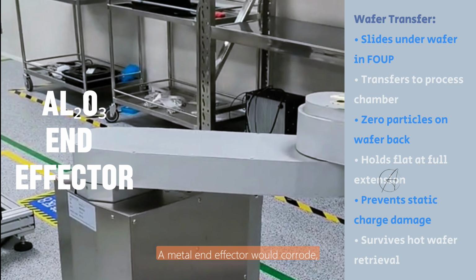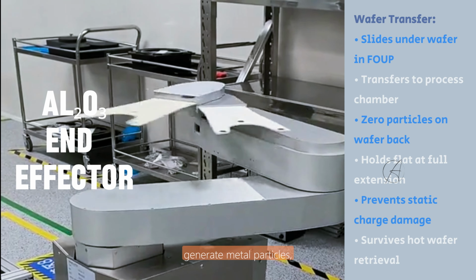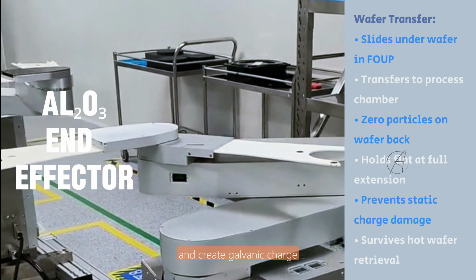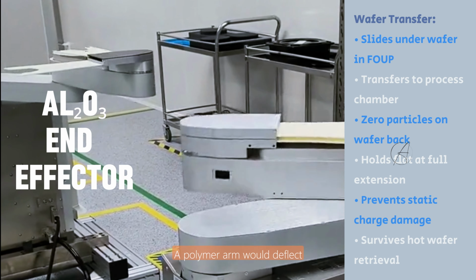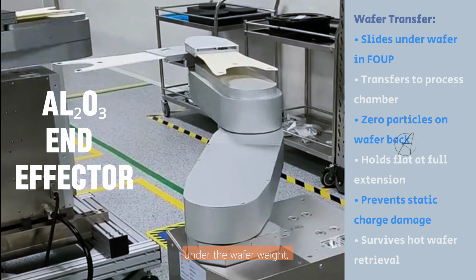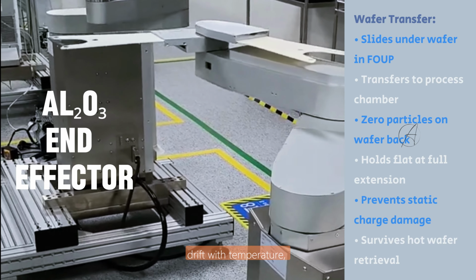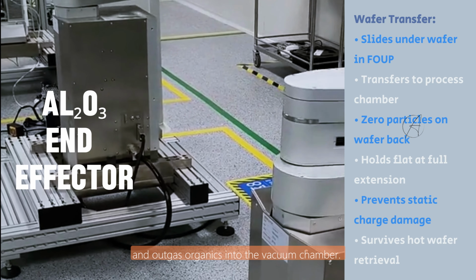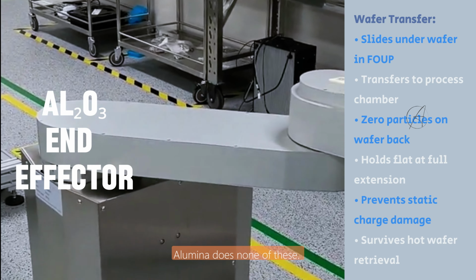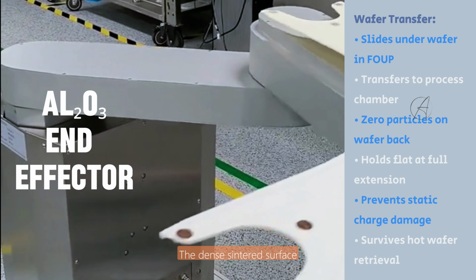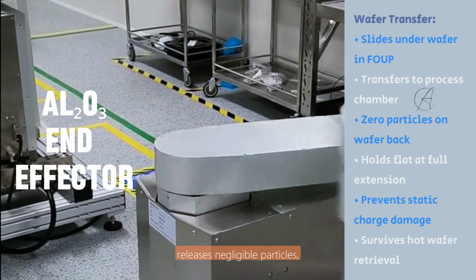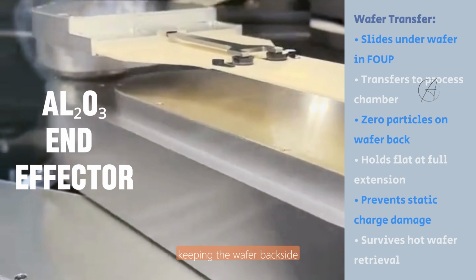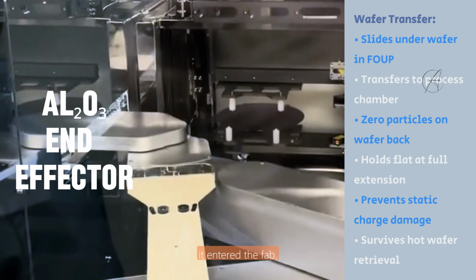A metal end effector would corrode, generate metal particles, and create galvanic charge on the wafer surface. A polymer arm would deflect under the wafer weight, drift with temperature, and outgas organics into the vacuum chamber. Alumina does none of these. The dense sintered surface releases negligible particles, keeping the wafer backside as clean as the moment it entered the fab.